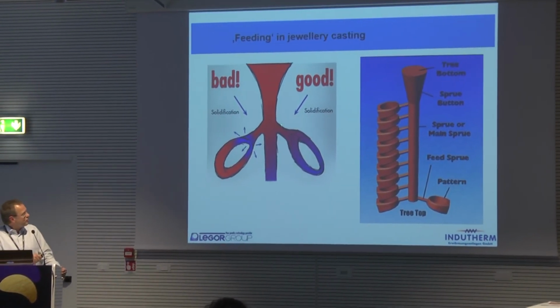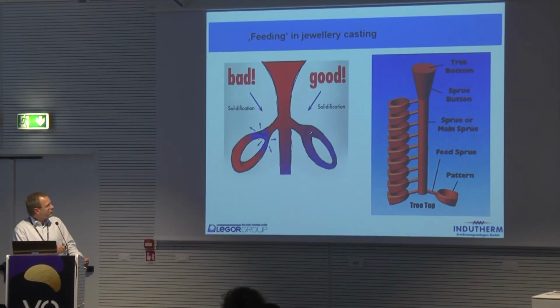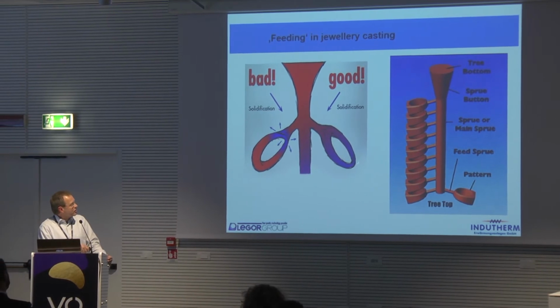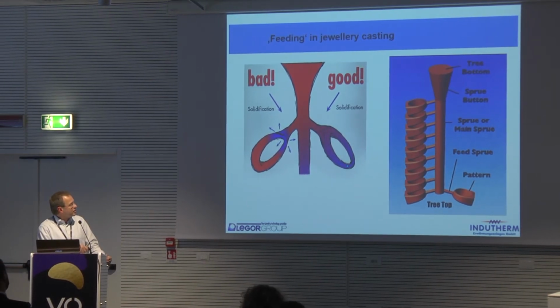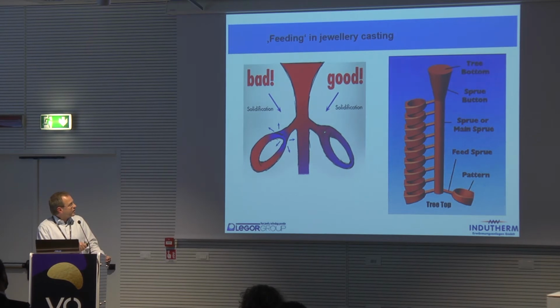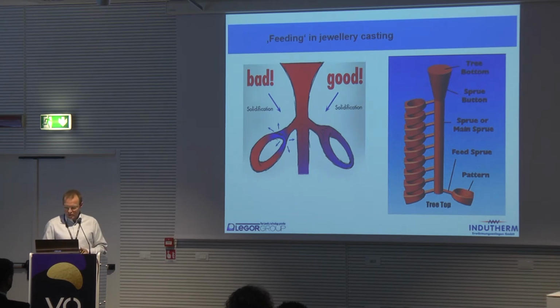Just opposite, if we put the sprue on the more heavy part of the ring, solidification will start here and progress entirely around the ring shank. So this will allow molten metal to feed the solidifying part of the ring and will minimize, or in the best case, avoid shrinkage porosity.